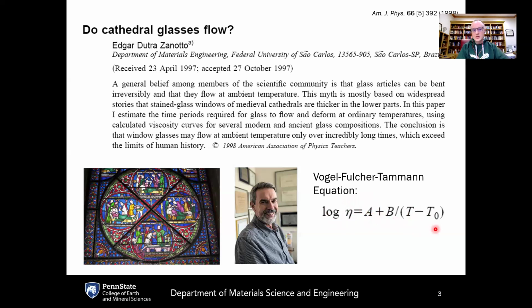And he used this equation considering several different glass compositions, then to extrapolate this viscosity down to room temperature, because the viscosity at room temperature is much too high to measure directly. And so this can only be done by measuring viscosity at higher temperatures and then extrapolating down to room temperature.